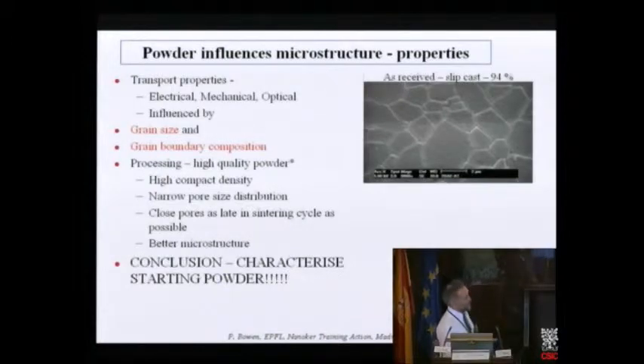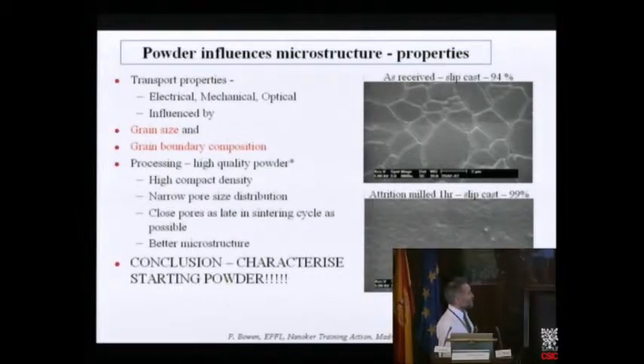If we look at the microstructure of the ceramic, as sintered, slip cast, you get 94% density, and you have this huge distribution of grain sizes of several microns. It's the same powder, just attrition milled, same scale, and we get 99% density, and we see grain sizes are now generally below a micron. So this small tail of agglomerates totally modifies the way the particles pack, the way they sinter, when we start closing porosity, and consequently the properties of your ceramic.